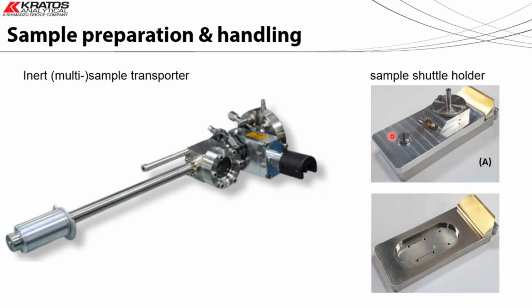They essentially have an evacuable volume here. So they're just evacuated through this one-way valve using a little hand pump. And it's not a brilliant vacuum, but it does allow you to transfer from a glove box to the instrument, evacuate that, lift the lid off the sample holder, and then your samples can just be analysed under the UHV conditions.